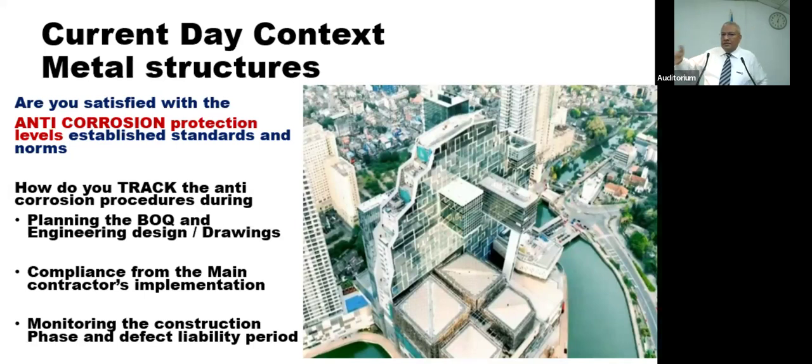It's good for the country also, because it is our country. We have a particular C5 category. We will be doing it. Like these bridge components, they were reblasted, repainted, and then installed. So the Spanish company had two costs. One is blasting and painting in Spain and sending the material. The second, after seeing the corrosion, they reblasted and repainted to 400 microns. 320 is the minimum DFT shown there. And then everybody is happy. Now no corrosion.